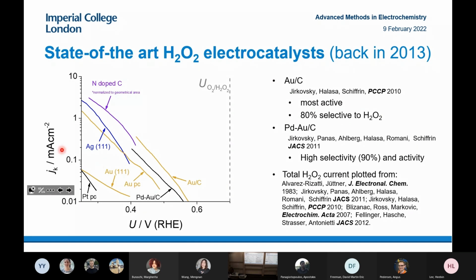And what they proposed was that, anyway, we were looking at the state of the art. This is experimental activity as a function of potential for hydrogen peroxide. You can see the most active catalysts are gold, and palladium-gold also works quite well, similar to gold, slightly more selective than gold, and also nitrogen-doped carbon. This is work from Tim Fellinger and Marcus Antonietti. But looking at the state of the art, no catalyst could actually reduce oxygen to hydrogen peroxide at low overpotentials. So we thought, and our theoretical collaborators thought, it should be possible to do this reaction and get what we'd call the ideal catalyst.